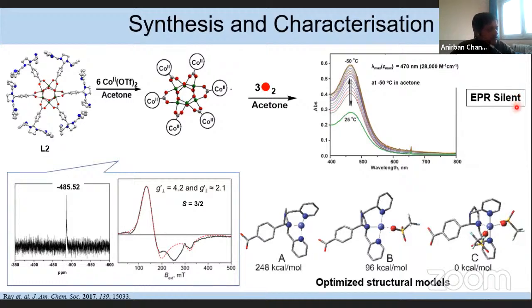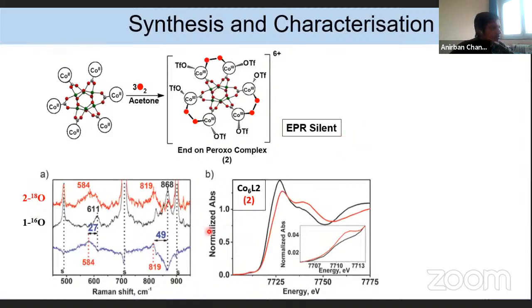To know more about the geometric and electronic structure, we did the resonance Raman experiment and also the X-ray study. In the resonance Raman experiment, we get two isotopically sensitive vibration bands at 868 centimeter inverse when we use 16O2 and 611 centimeter inverse. These two bands downshifted to 819 centimeter inverse and 584 centimeter inverse in presence of 18O2. The 49 centimeter inverse downshift corresponds to the O-O stretching vibration of the peroxo bond, whereas the 27 centimeter inverse shift corresponds to the metal-oxo stretching vibration. And this data also fits very nicely with the DFT calculated parameters.